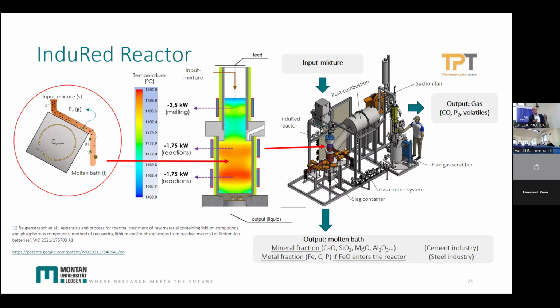So you even see the necessary heat. The big share of heat to put in is to melt the ash, more than, in this case, 50%, but it can be even more. So you can reduce this share if you combine the thermal pre-treatment and feed the hot ash into this reactor type, and you can save this money for this energy. And then you have the proper temperature for the chemical reactions. It's a very simple figure on the left-hand side, because we have a solid phase, we have 2 liquid phases, slag phase, metal phase, and you have a gas phase. Sometimes it's a question of the viscosity of the materials. You have a film like shown here, but sometimes you have droplets on the graphite particles, and that changes the chemical reaction.